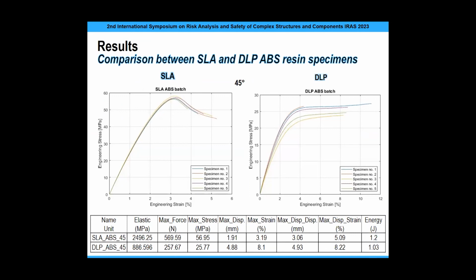The Shimadzu software gave us a table with the different parameters of mechanical properties, and we additionally processed them in MATLAB software, so we could make these stress-strain curves. In comparison of both of them, you can see the difference. Although it is the same material, ABS-like resin, the parts were made with different technology, so the mechanical properties are very dependent on the technology. You can see the curves are not the same, and this batch of 5 specimens has very good repeatability here, and not such representative repeatability here for the DLP batch.